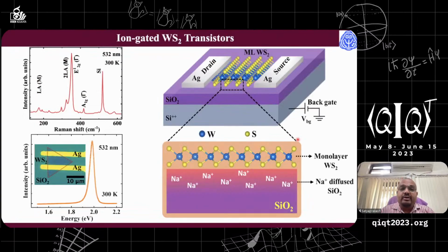And now I'm going to discuss some of our recent results about this WS2 transistor. The WS2 transistor is interesting because, unlike the MoS2 transistor, where I have shown the hysteresis is not that wide, here the growth process is the same. The only thing is that we have kept the substrate-to-precursor distance closer. By doing that, we have pumped or injected a larger number of sodium atoms into this silicon dioxide substrate, the one I am showing in the cartoon.